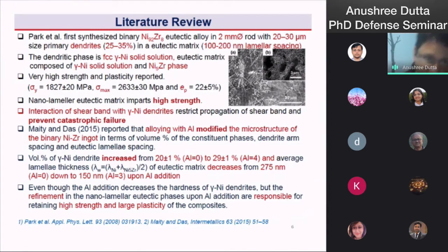These alloys exhibited excellent room temperature mechanical strength and plasticity, with yield strength up to 1.8 GPa and ultimate composite strength 2.6 GPa with plastic strain 22%. The nanolamellar eutectic matrix imparts high strength, whereas the interaction of the gamma nickel dendrites with shear bands prevents catastrophic failure.